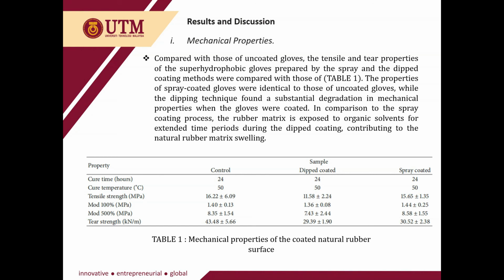In comparison to the spray coating process, the rubber material is exposed to organic solvents for extended time periods during the dip coating, contributing to the natural rubber material swelling. As we can see in table 1, these are the mechanical properties of the coated natural rubber surface. Here are 6 properties. As we can see, there is cure time, the cure temperature, the tensile strength, the modulus at 100% in megapascal, the modulus at 500% in megapascal, and the tear strength.